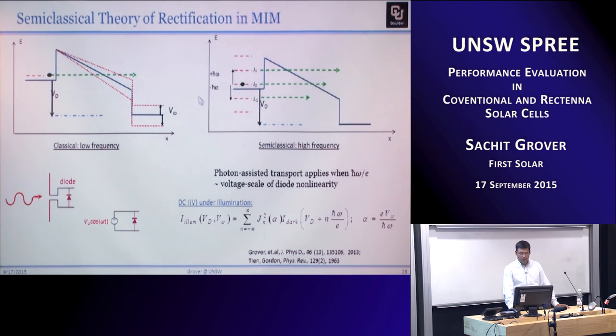When we go to the high frequency regime, we have to invoke the semi-classical theory where the electron now absorbs a photon or emits a photon and can occur at a multiplicity of levels which are spaced apart by h bar omega relative to its original state. And this is a theory which is used in microwave rectifiers, and it was established in 1963. What it basically says is that because of this phenomenon called photon stepping or photon-assisted transport, your illuminated IV curve can essentially be given in terms of the dark IV curve, but add to the voltage the energy of the photon, and you have to weight each of those IV curves with this Bessel function term.